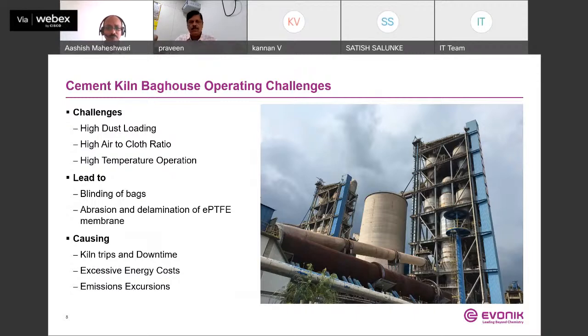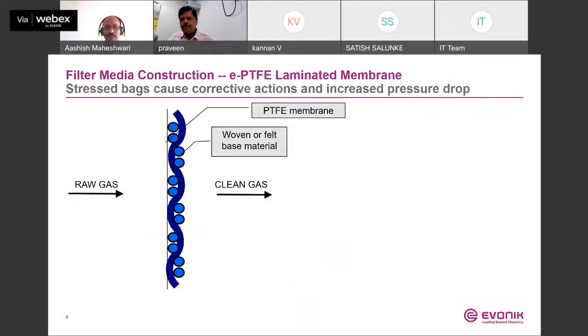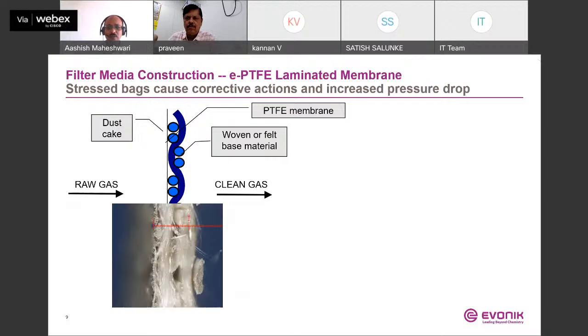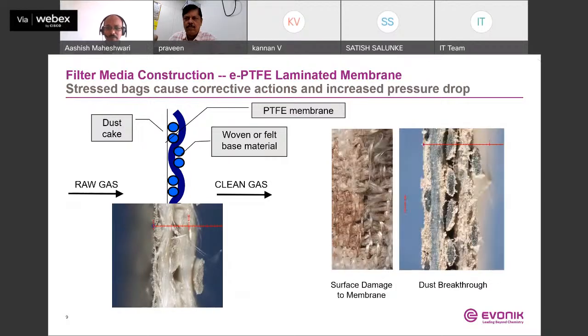To avoid this, basically there are two types of filter media, as everyone is aware. In one filter media, glass has been put as a screen and on that a thin PTFE layer has been applied, which does the filtration job. This is how the structure looks. The major challenges are surface damage and mechanical breakdown, with dust passing inside the PTFE membrane.